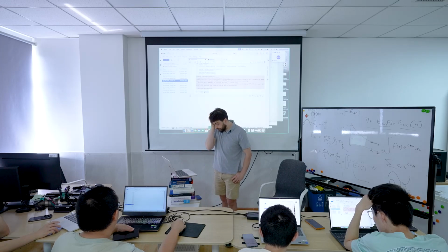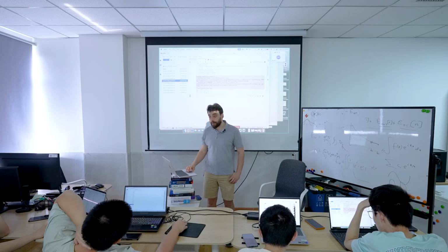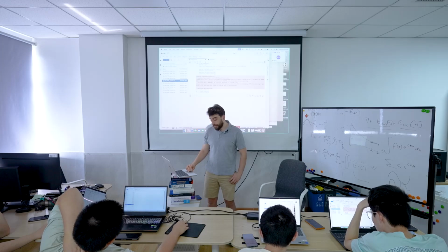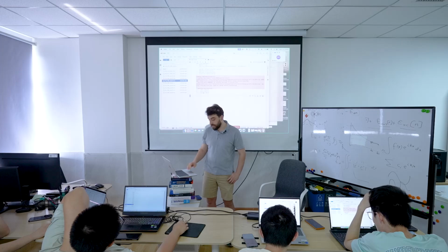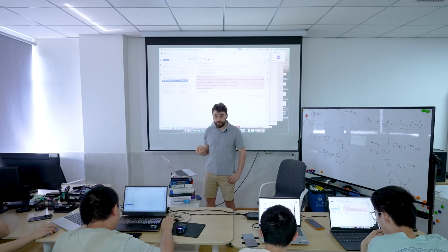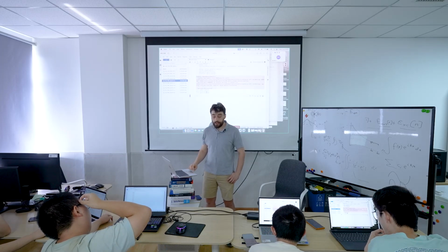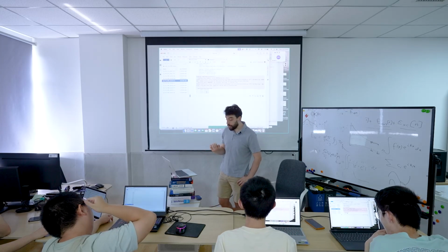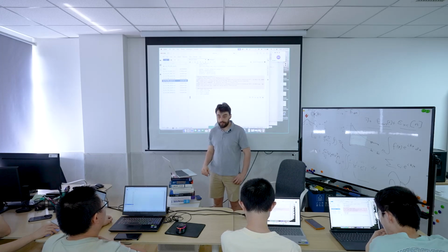And the output to screen tells us that our 111 gamma point calculation has this energy. Our 222 calculation is about 10 eV different. Okay, which is a huge difference. Okay, it means that we are definitely not converged. So remember, our arbitrary tolerance that we're setting today is 10 to the minus 2, right? And this difference is 10 to the 1, right?